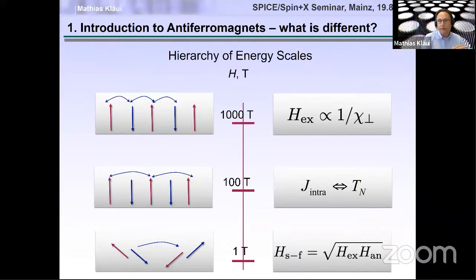And due to a Dzyaloshinskii-Moriya interaction, something I didn't mention here. In antiferromagnets, you can have Dzyaloshinskii-Moriya interaction. But what is very important to tell the community is that in an antiferromagnet, what DMI does is it cants the two sublattices to generate a weak magnetic moment. It doesn't lead to spiralization, the typical intersublattice DMI. If you want to have spiralization, to have antiferromagnetic antiskyrmions, then you need the so-called Lifshitz invariants, or some people call it inhomogeneous and homogeneous DMI. But you have to be very careful: if the DMI is between the sublattices, it just cants the moments a little bit, generating a weak moment. If you want spiralization, you need this Lifshitz invariant. That's something people are interested in, and we are looking into how you can get and vary the DMI. It's a materials property that you might be able to tune.